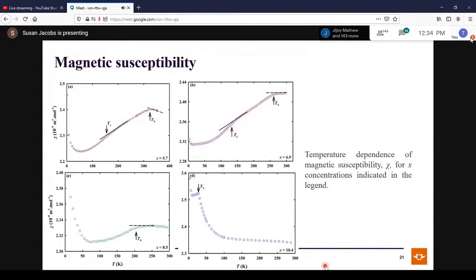Okay, the next measurement that we usually do is magnetic susceptibility measurements. So here we can see a change of slope happening at Tn, and this Tn then corresponds very well with the Tn that we determined from electrical resistivity measurements. So in all these curves, I've only shown representative samples again.